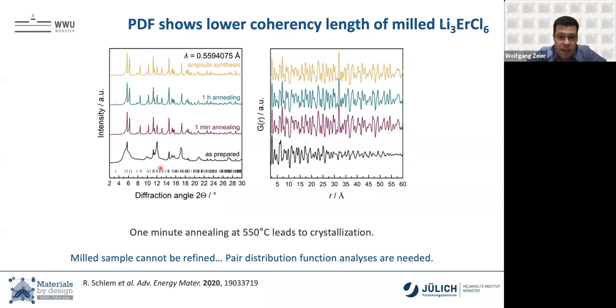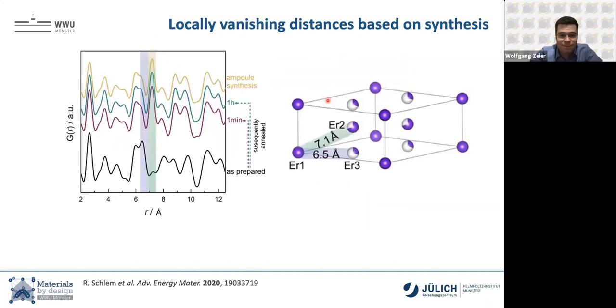So we need to look at the pair distribution function of these materials. And PDF is in the end just a histogram of atom-atom distances, and this can help us. We can refine these or even look at them qualitatively, and we'll do that now. For instance, you see that here the PDF, so this atom-atom histogram, trails off really fast, loses intensity. It tells us that it's pretty much an amorphous, some sort of glass-like material, whereas crystallization gives us really crystalline pair distribution functions. Let's look at them first qualitatively.